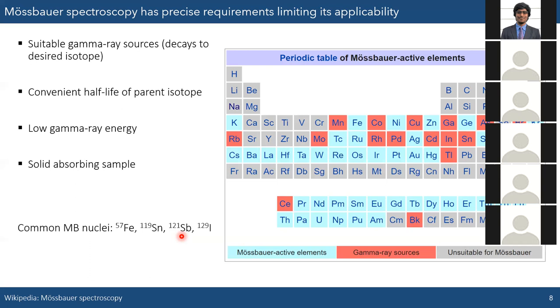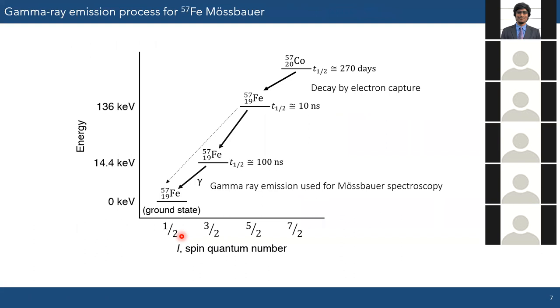How is the source excited? So the source itself doesn't actually have to be excited at all. The source is a radioactive material, and so over time it will undergo radioactive decay and emit these gamma rays. That's a requirement on these source materials: to have a convenient half-life, not too short or too long, so you are getting a reasonable amount of gamma rays being emitted per minute, per second, and so on.